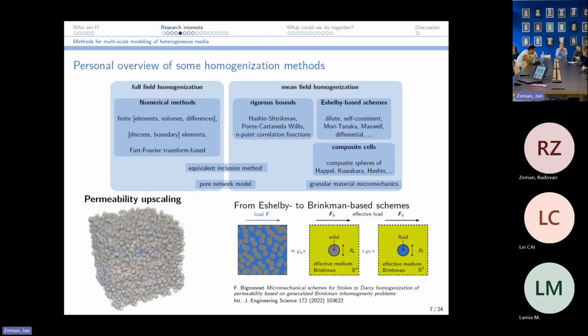And the idea would be, for example, to represent that type of microstructure with solid grains in gray and pore phase. You would use some representative inclusions or morphological patterns, maybe a sphere for the solid immersed in the effective medium, a sphere or a cylinder for the fluid immersed in some effective medium. And then you do some averages based on the solution to these much simpler individual problems. And from that, you can get, in some situations, very good estimates of what you have from full field simulations. But now, instead of spending 1 hour doing computation, you have 1 millisecond.